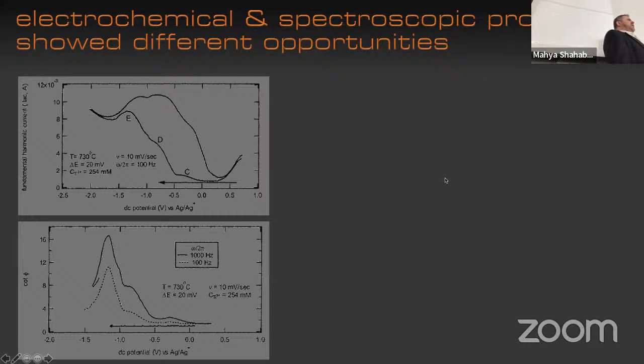First, electrochemically, we wanted to see, maybe we could have a probe and see some differences between the ways that you can detect different concentrations of 3+ versus 2+. And so what you're seeing here is an AC voltammogram. So we're taking a DC ramp, and then we're putting an AC ripple on top of it, and then we're reading the AC currents. And what that does is that gets some of the thermal noise out of your electrochemistry. But actually, more importantly, and this is what I was pointing at here, you look at the top scan, and yeah, you can see you're looking at shoulders, you're looking at all these other things.